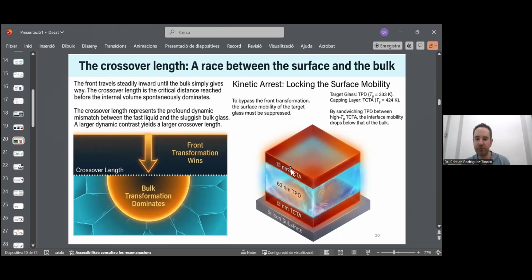There is another strategy which is more intelligent, let's say, which is capping the surface. Imagine this is the glass we want to study, TPD, which has a glass transition temperature of 333 Kelvin. We go above this temperature to study the devitrification of this TPD, but we see that on the surface, the transformation will start earlier. So what can we do? We put on top of this TPD another material with a higher TG, okay?